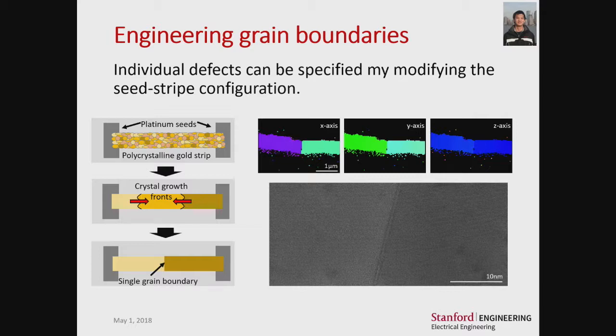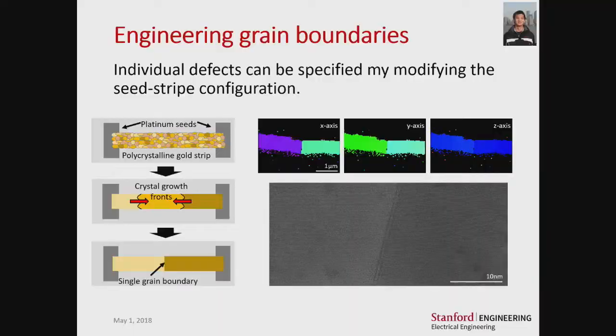So in this case, we can see from EBSD and high resolution TEM that we can produce really high quality bicrystals with extremely clean grain boundaries. Talking to people in material science, it turns out to be a real challenge to produce very well-defined single defects in, for example, bicrystals. And it's not just looking at single grain boundaries, but potentially situations with multiple grain boundaries, and ways of controlling crystal orientation.